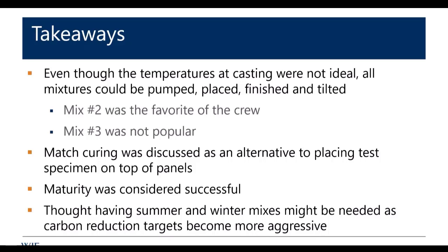And those of you familiar, match curing is where you basically monitor the temperature of the slab. You have a box that duplicates the temperature that the concrete is experiencing, and so you get an actual representation in your test cylinders. Some could say, well, why not just use maturity? And most people think that's great, but most are hesitant to tilt the panel without actually busting the cylinder. The crew is saying, no, we need to know that when we tilt it.